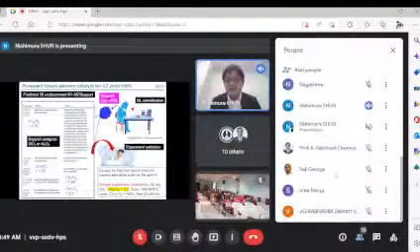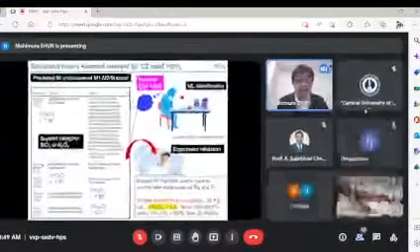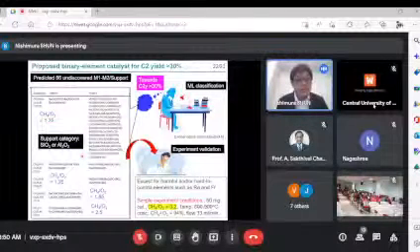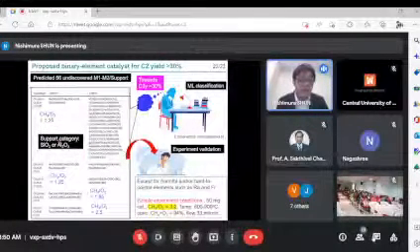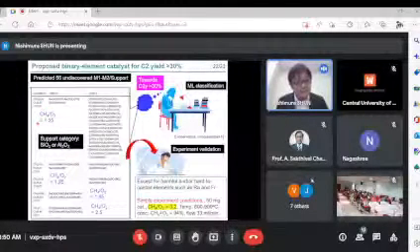There is a list of the predicted 56 undiscovered binary element supported catalysts with favorable reaction parameters on the basis of literature data-driven machine learning classification. In all cases, machine learning proposed silica or alumina as the good candidate for support. And interestingly, in all cases, the methane to O2 ratio is really small, below 2.